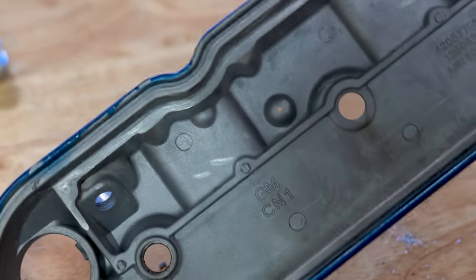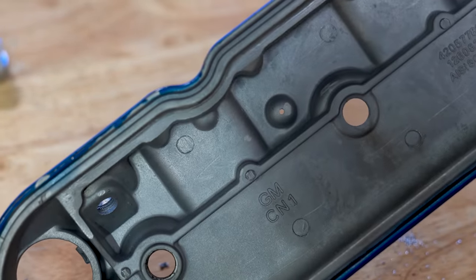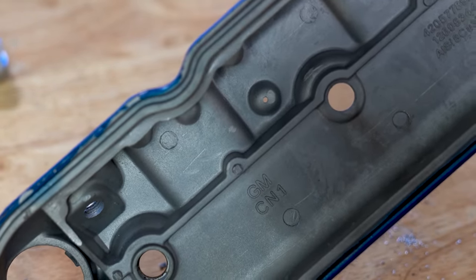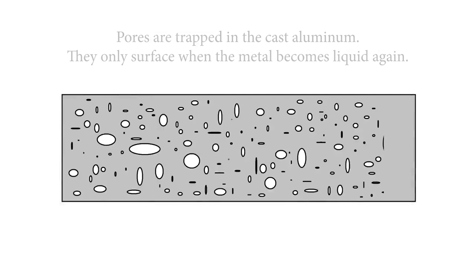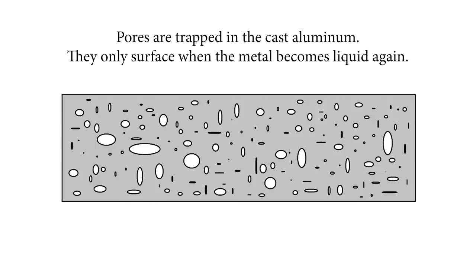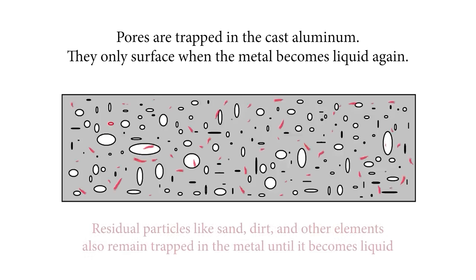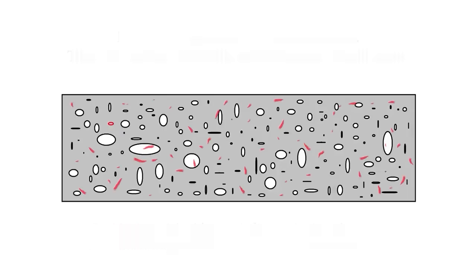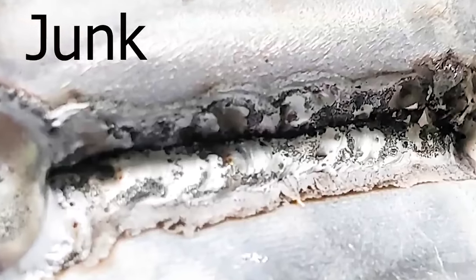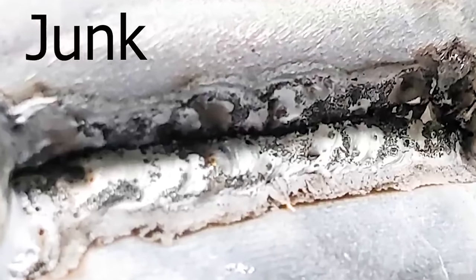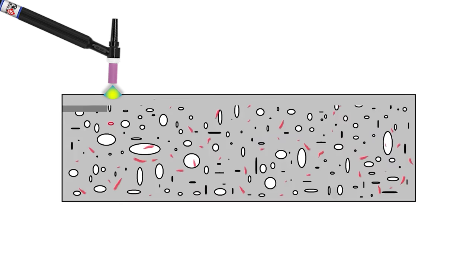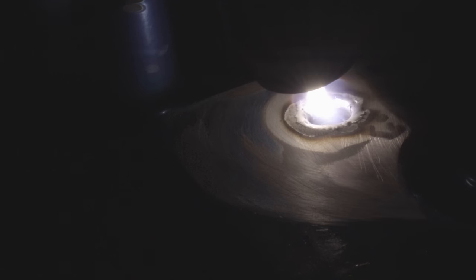So make sure that the relief hole goes in there if you're welding a blind hole. Cast aluminum can be a relatively tricky metal to weld because it has several pores contained within the material itself. Those pores, combined with the residual casting particles, all combine to create a very pesky byproduct, which we often refer to as junk. In order to make a successful weld, we first have to run the torch over the top of the casting to push out any junk below the surface. This allows a fresh layer of aluminum to form on the surface, which we can weld to. You have to basically recast that layer before you can weld to it.